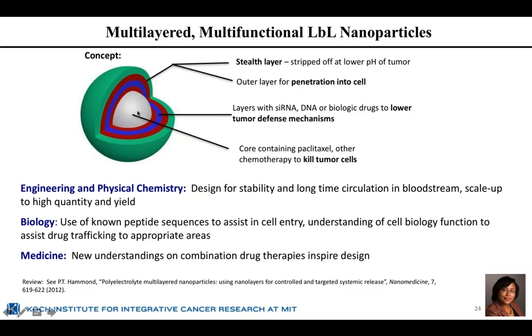So in this case, we incorporate our chemotherapy drug in a nanoparticle that is familiar to us. For example, we can use a liposome, we can use a PLGA nanoparticle. As long as that core particle has charge, negative charge, which is what we use most frequently, then we can layer around it. So we wrap up our drug in the core, and then we adsorb around the core layer by layer film. And in our case, we typically look at 2 to 4 layers.